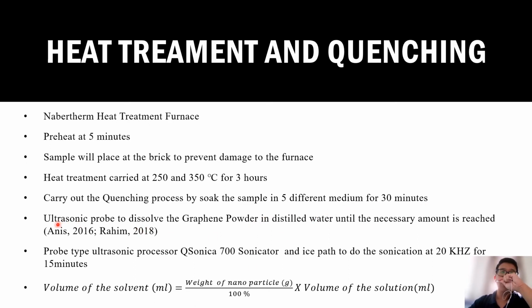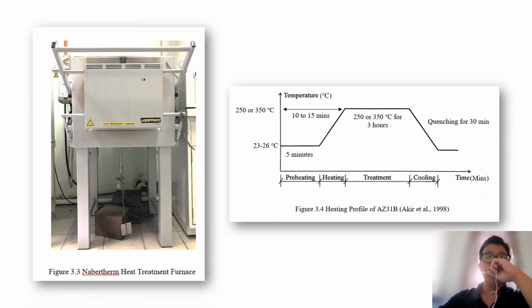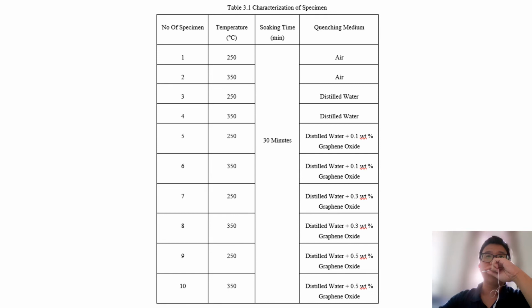To get the solution that consists of graphene oxide, an ultrasonic probe is used to dissolve the graphene oxide powder in distilled water until the necessary amount is reached. Then, using a probe type ultrasonic processor, the Qsonica 700 sonicator, and an ice bath, the sonication is done at 20 kHz for 15 minutes. To calculate the volume of solvent, you can use this equation. These are pictures of the heat treatment machine that we will use and the heating profile of AZ31B. And then this is the table of the specimens.